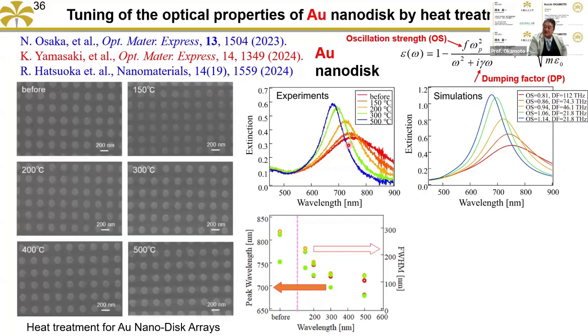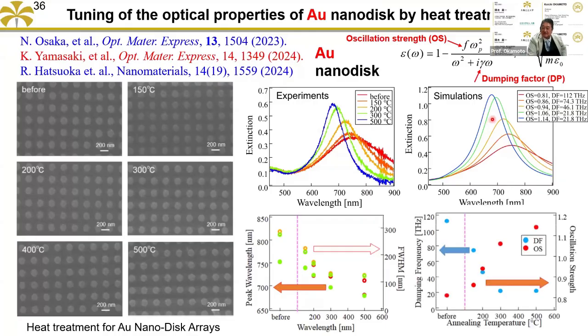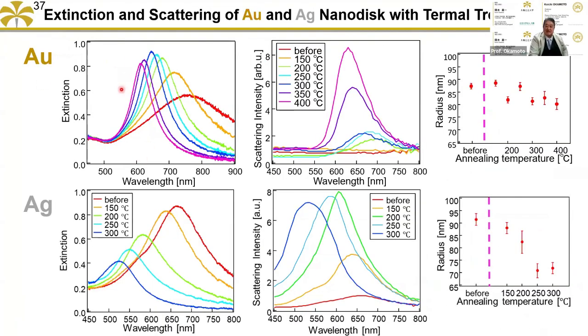Then we can reproduce that result by changing the metal parameters. We found that the oscillation strength of the metal dielectric function increased with increasing temperature, and the damping factor became low. That means that by the heat treatment, the metal crystal quality becomes higher. That's important. And this is the extinction, and this is the scattering image.